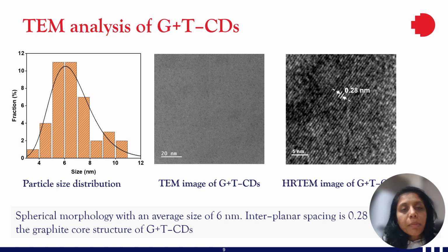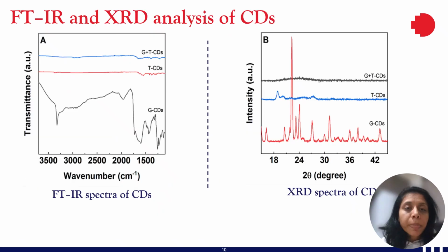The size of the carbon dots was measured using high-resolution transmission electron microscopy, and we could see that the carbon dots displayed spherical morphology with an average size of 6 nanometer. The interplanar spacing distance of 0.28 nanometer indicated the graphitic core structure of glutamic acid and tryptophan carbon dots.